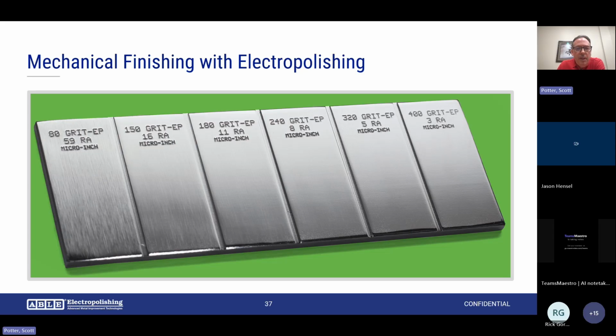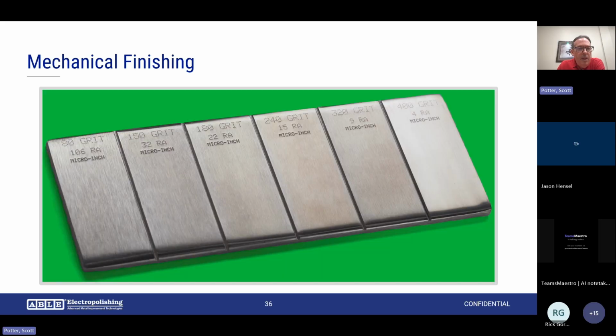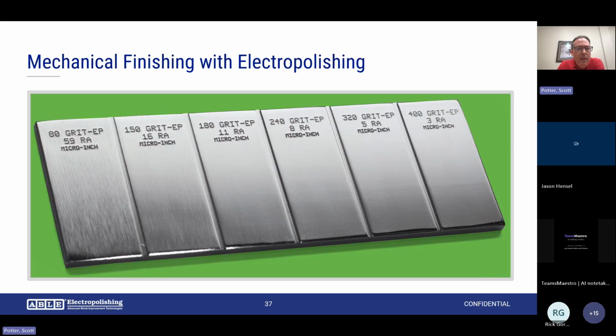See, it goes 59 all the way down to a 3. I'll go back to the last slide. You see where you start out at 106, went down to about a 4. You can see the improvement with the electropolishing. This is typically with 1,000 stock removal.